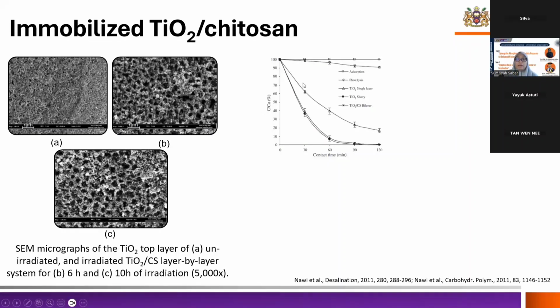So then we compare. This is titanium only, without the presence of chitosan. This here is the titanium dioxide and chitosan. And we observe that the photocatalytic activity of the titanium dioxide chitosan is almost comparable with the TiO2 in powder form. We have done characterization, and we found that during the irradiation, the chitosan also undergoes some transformation. There are some carbonyl groups being formed on the chitosan surface, which increase its visible light activity. That's why we observe that the activity of the titanium dioxide chitosan bilayer is almost comparable with the slurry TiO2.